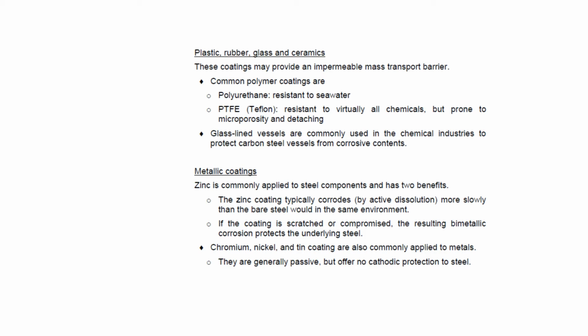Slight issue is that they can be more fragile because you might be looking at layers of quite brittle materials in the case of glass. In the case of Teflon, you have some potential problems with detachment of the layers.